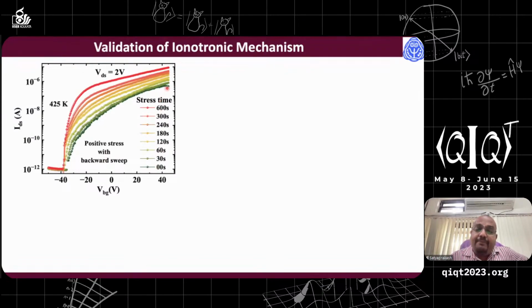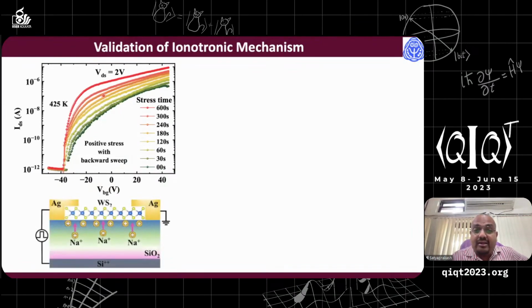And while applying this positive stress, wait for different times. These are the waiting times before you start the experiment by applying the 40 volt. You can see here, as the wait time increases, the hysteresis current is also increasing. This is because when your wait time is more, you are pumping more mobile sodium ions near the interface, and they additionally release some kind of electron cloud around them into the WS2 channel. Thereby this trend is noticed.